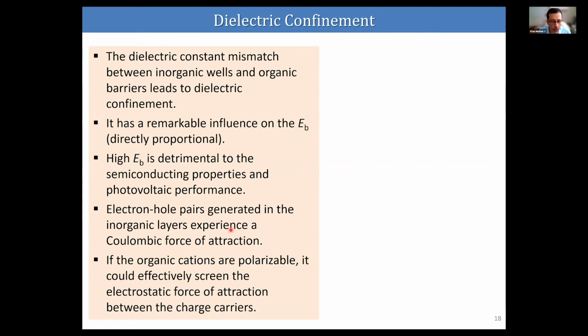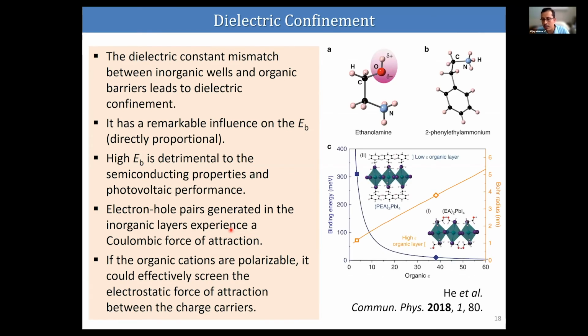So if we can use polarizable organic cations, these organic cations can screen this electrostatic interaction between the charge carriers or the excitons very effectively, and that can reduce the exciton binding energy. So that was the basic idea, and this was actually not our idea. In 2018, it was already proved in lead-based perovskite material. Professor He and co-workers used the ethanolamine and 2-phenyl ethyl ammonium cations, and the ethanolamine has a very good polarizability, and the other one doesn't have a good polarizability.